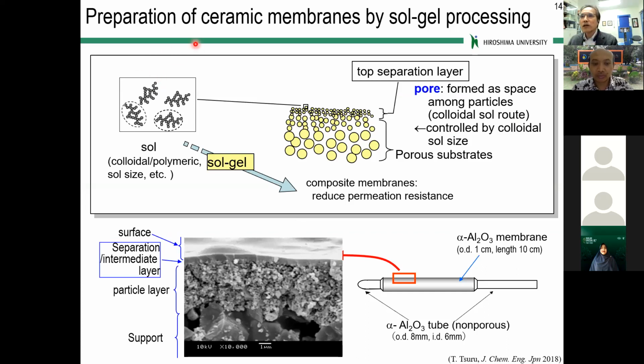Now here we have the concept of our ceramic membranes prepared by sol-gel processing. This SEM picture indicates a typical membrane cross-section. Again, the support. Here we have the 1 micron scale bar. There are alpha alumina particles, and some space is the pores of this support. On this support, a particle layer is coated to form the second layer. On this particle layer, we further coated the intermediate layer and the separation top layers.